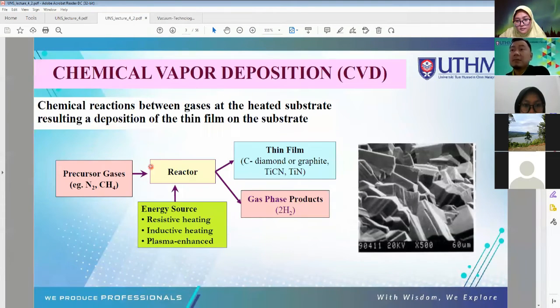Okay. For chemical vapor deposition, we have a chemical reaction between the gases and the heated substrate, resulting in deposition of a thin film on the substrate. What we have here is a precursor gas, for example nitrogen and CH4, methane, and then we have a reactor. After we put the gas inside this reactor, we apply energy to get some heat and some chemical reaction. It can be resistive heating, inductive heating, or a plasma enhanced process. By having this energy source, we can create a chemical reaction, where the output of this precursor is a thin film.